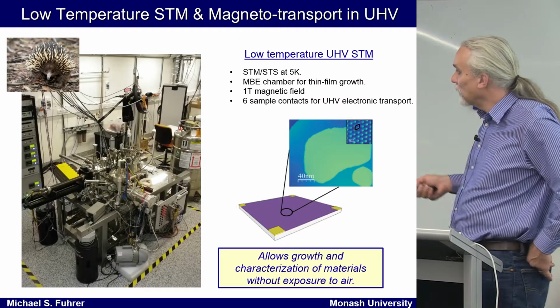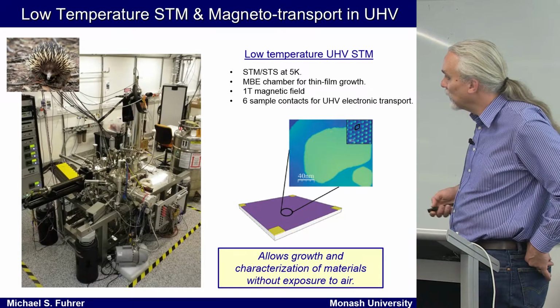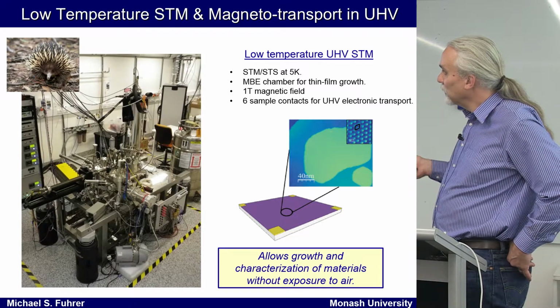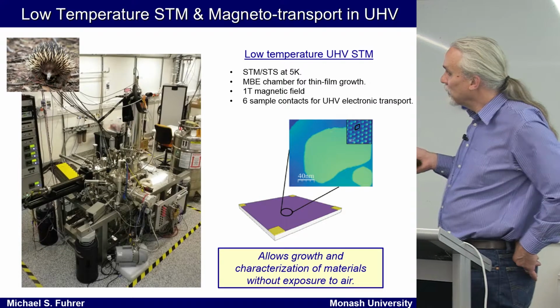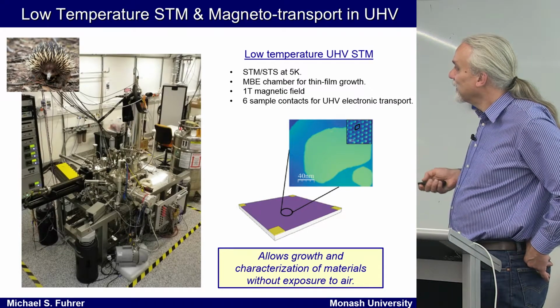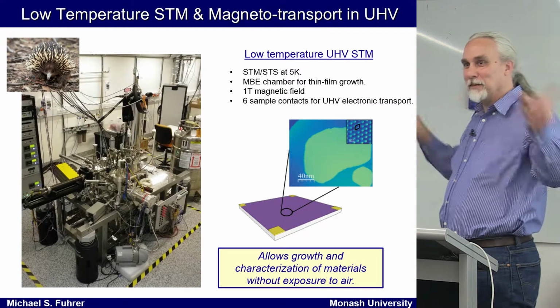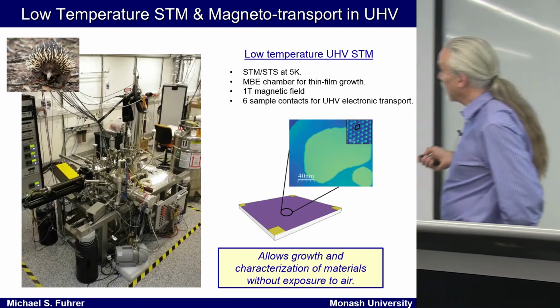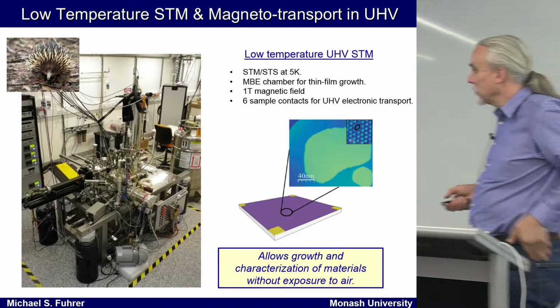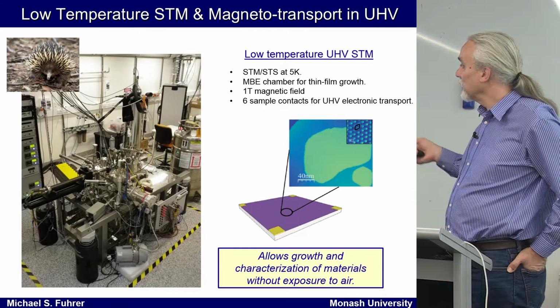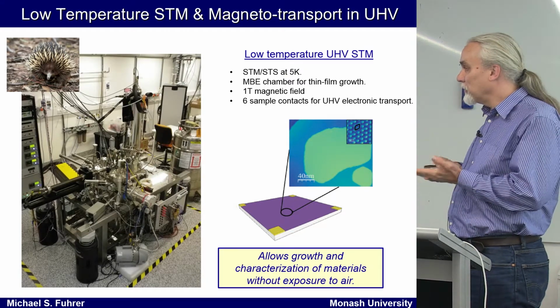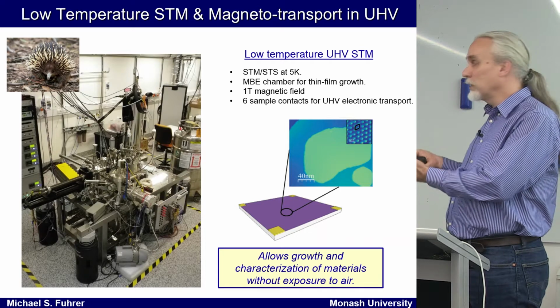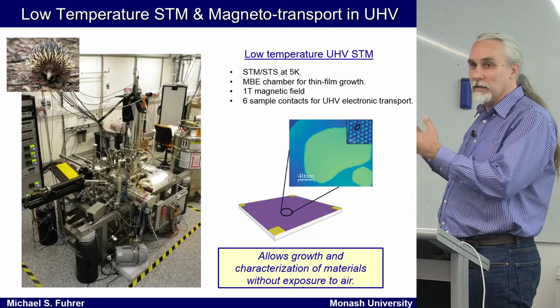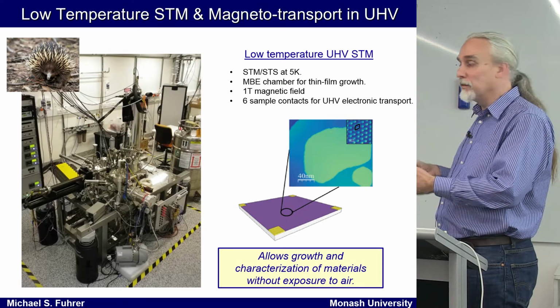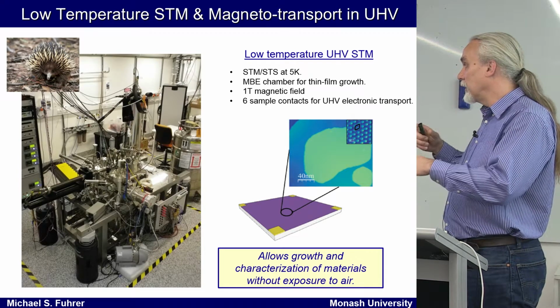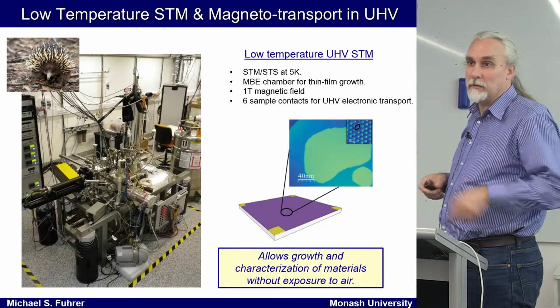So if you go over to New Horizons and look in the window, you'll see this machine here, which Mark, my postdoc who's here, calls the echidna, because it has lots of spiny projections coming off of it. So this is a great machine. It allows us to grow materials like this sodium-3 bismuth, and then transfer them into a scanning tunneling microscope at low temperature, where we can not only look at all the atoms in the material, but we can also do electrical experiments on that material.